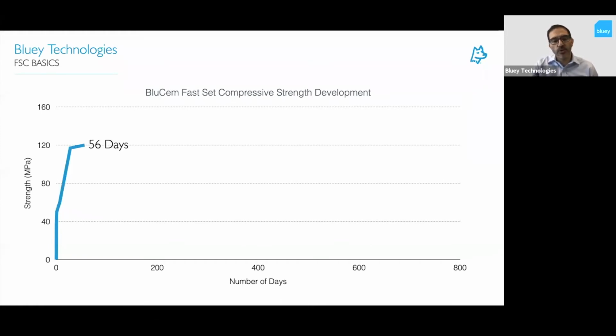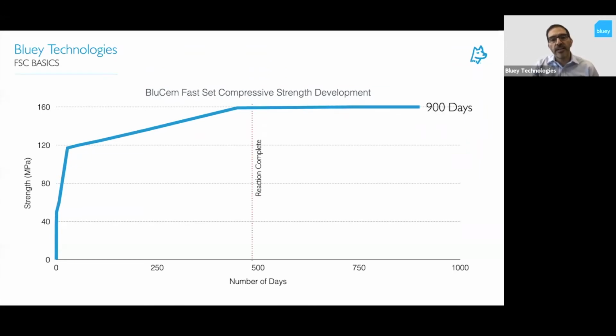But long-term strength gain is actually really important in these products because the reaction actually continues over a reasonable period. In fact, the strength keeps gaining for many days. You know, we've gone past our 28, 56, 112, 224, 448 days, and we're still seeing a strength gain. So there's still something happening within the product. There's still a reaction occurring. And we know that doesn't level out until around 500 days when the reaction is complete.